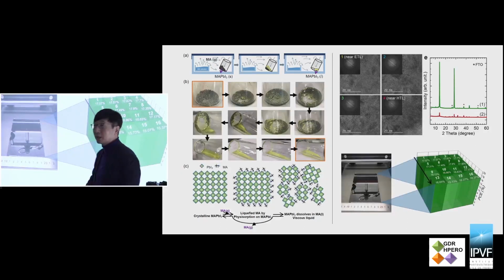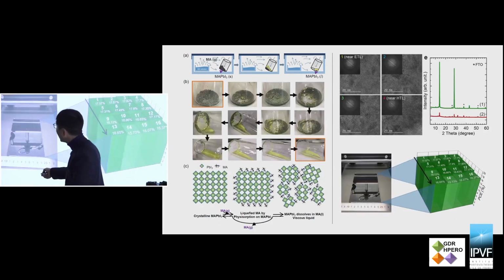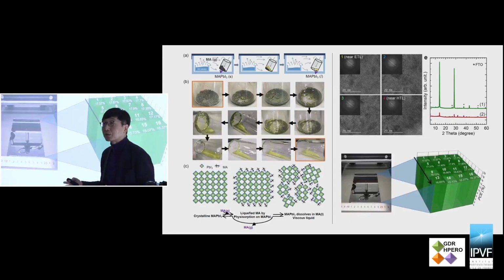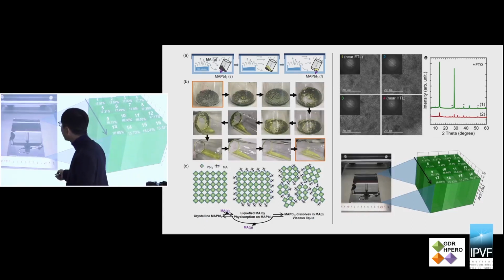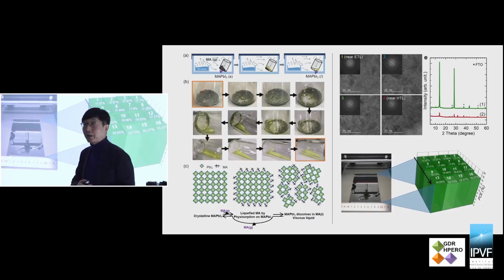So it probably looks like a liquid structure. It can dissolve some part of the perovskite powder, making some cluster form. We confirmed from the Raman spectroscopy that we still have the cluster of this perovskite phase. Because this liquid is very viscous, we diluted it using some acetonitrile, and then coated it using that kind of blade coat.